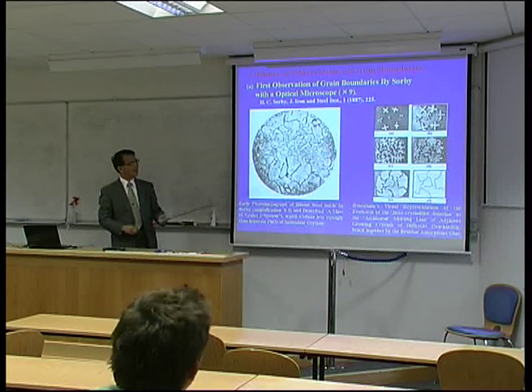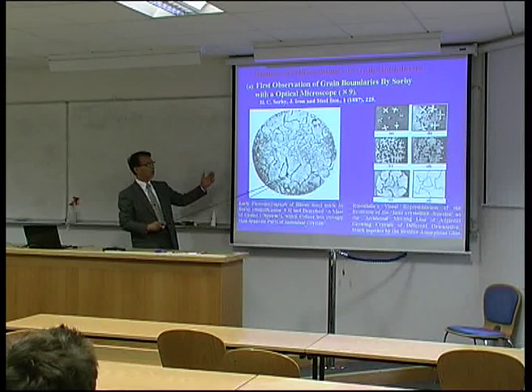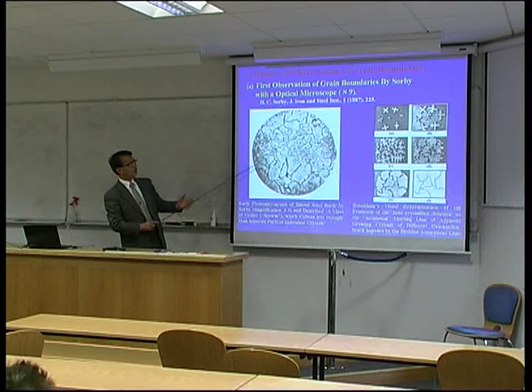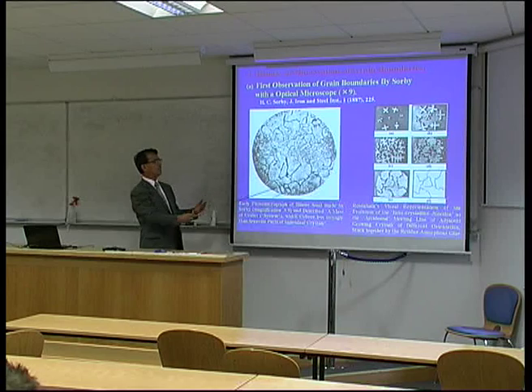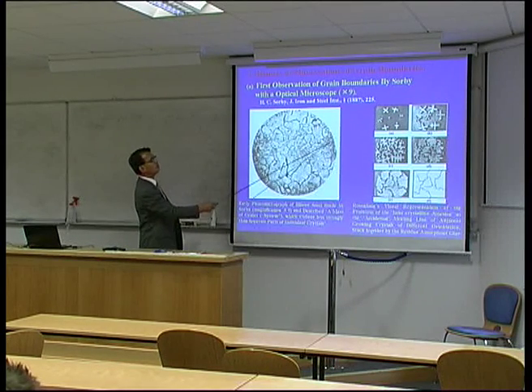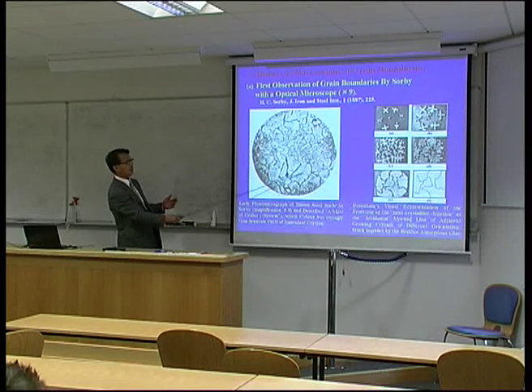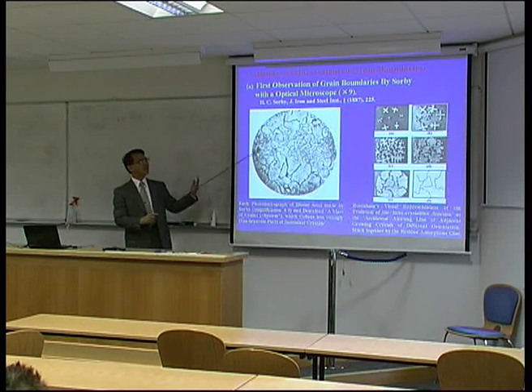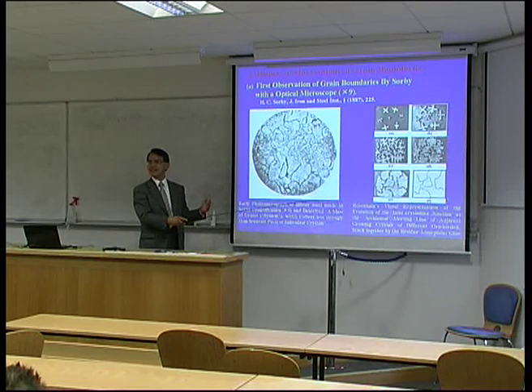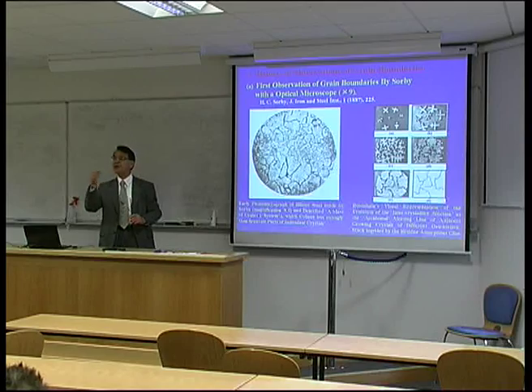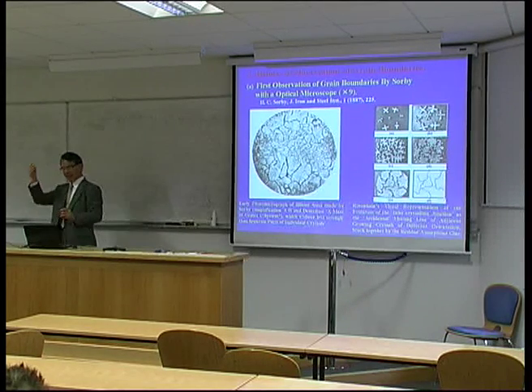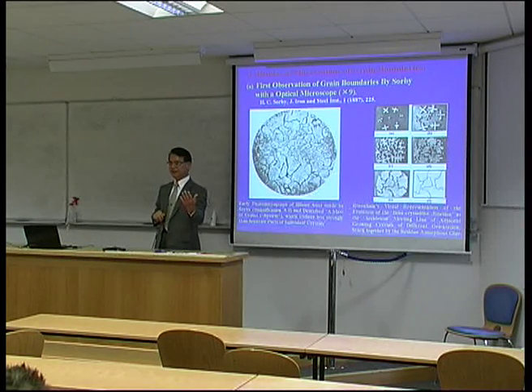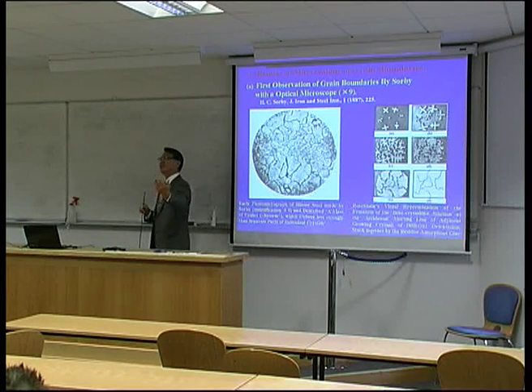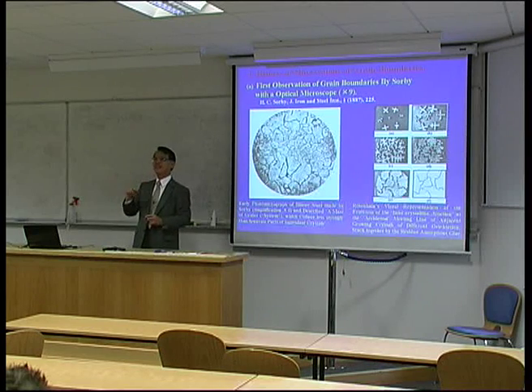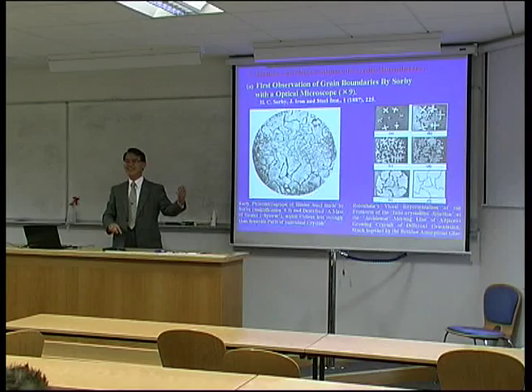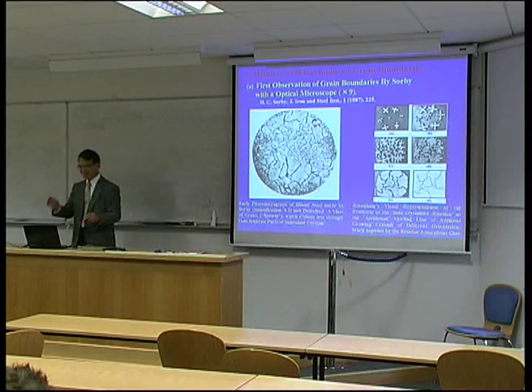And then, if we look carefully at the features of polycrystalline steel, of course the microstructure consists of a huge number of grains, but some areas consist of rather small grains, and some areas are rather coarse grains. Thus, this means the microstructure is not so homogeneous, but rather heterogeneous. This is the feature of most polycrystalline materials. But anyway, as I'm going to talk about later, if you study the effect of grain size on, for example, the strength of a material, often you use the average grain size. So what is the physical meaning of average grain size? It is rather suspicious, please remember this.